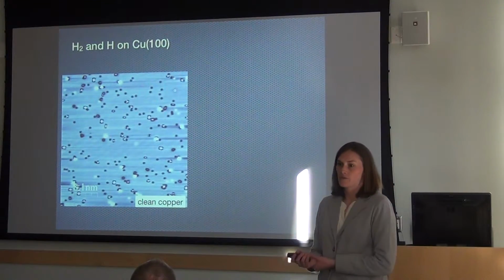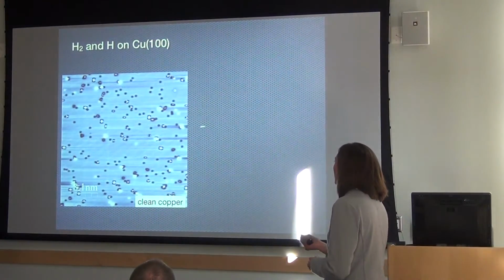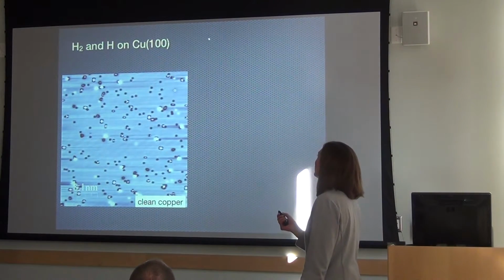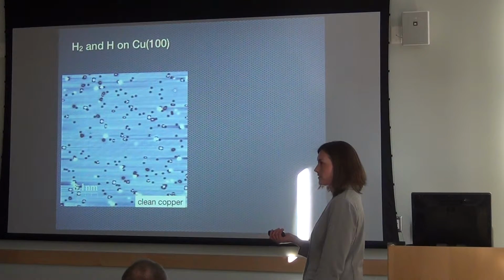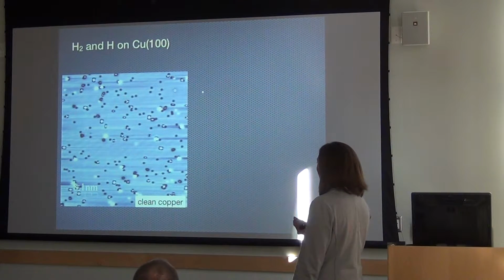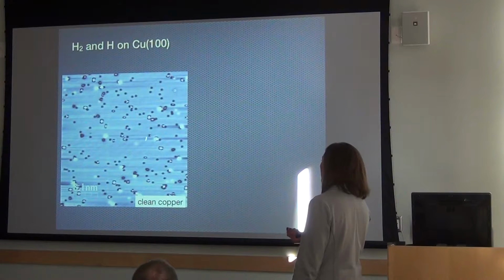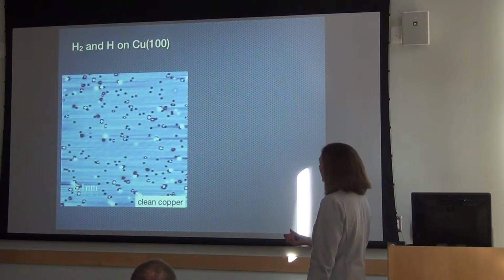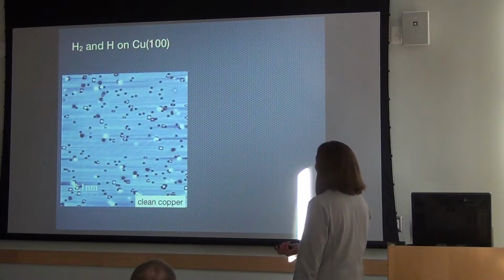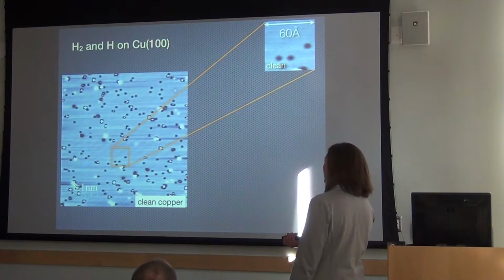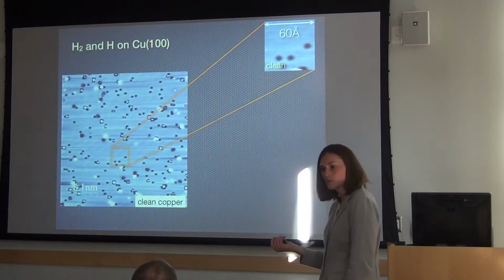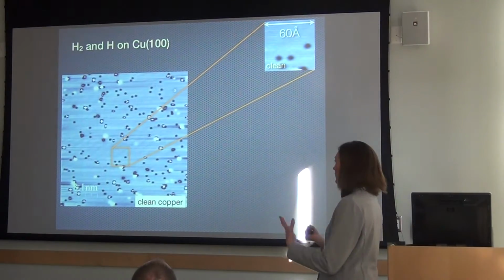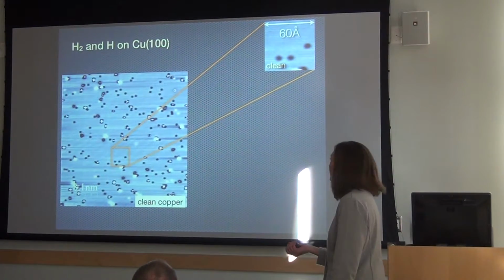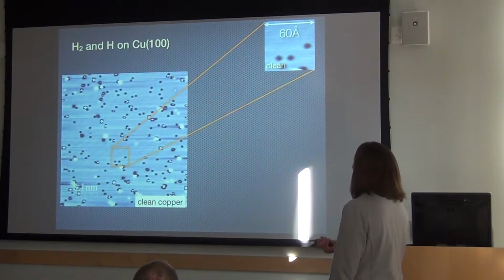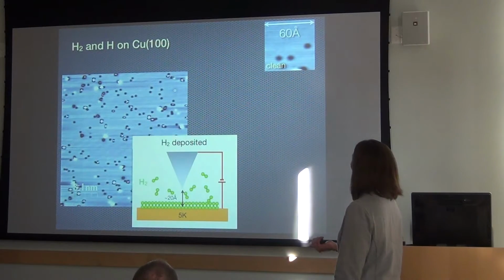And first we did this control experiment. So this is a different surface of a copper crystal. This is copper 100. I'll tell you in a minute why we use this surface. And this is clean copper. Everything on the surface is some kind of defect, but there are pretty large clean areas. And most of these defects are carbon monoxide, which is always hanging around in vacuum chambers. So it's going to be there in some amount. But here's a pretty clean region.